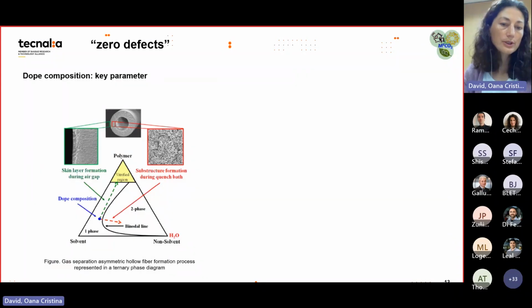As I said, dope composition is the key parameter, and this is like a ternary diagram. We usually have at least three components in this dope solution. The most important are the polymer itself and the solvent, and then we can have some non-solvent. We start with the dope composition given by the blue point. We already have some non-solvent inside because we want to be close to this boundary, the binodal line, which separates this mixture in two regions.